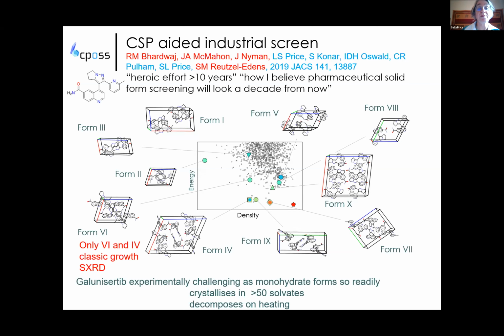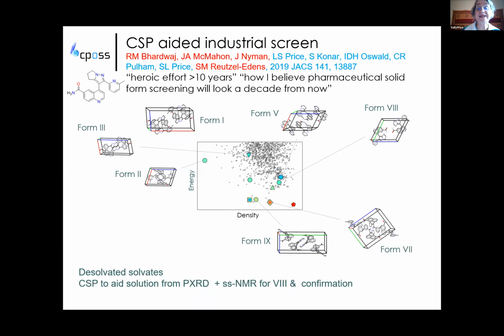So only 2 of the polymorphs could actually be grown into single crystals to solve by X-ray diffraction. And a lot more were found by desolvating the solvates, and you had to solve it from the powder diffraction pattern. And we also used calculated solid state NMR for helping solve those structures. But the big embarrassment, you can see, is that red global minimum, which was not found and should have been found. And so they commissioned some work of crystallizing this molecule under pressure and did find another polymorph, but not the global minimum.